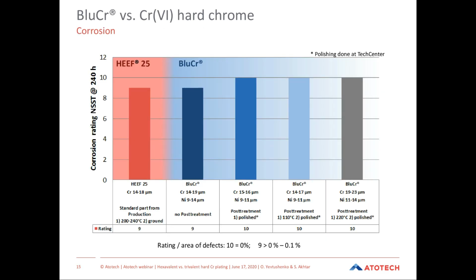So here on this slide, you can see the comparison of corrosion rating in the neutral salt spray test after 240 hours of testing. The comparison is done for parts deposited from hexavalent chromium, our benchmark HEEF 25, and blue chromium. In both cases, we have comparable chromium thicknesses on top. For blue chromium, we also have a semi-bright nickel underlayer for the parts.